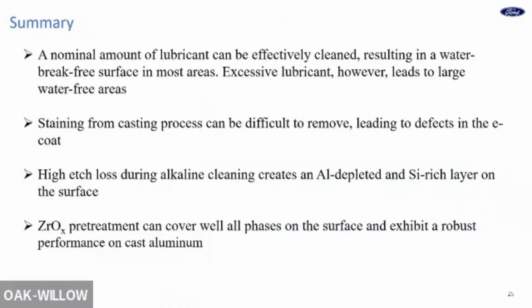With this, I conclude my presentation. First, the cast aluminum shows a bit higher etch loss in the alkaline cleaning and can have a higher conversion coating weight, but the performance is robust, especially with the nominal lubricant. If you put too much lubricant, it can potentially lead to some staining on the surface, make it difficult to clean in the solution, affect some adhesion, and also cause some defects in the e-coat.